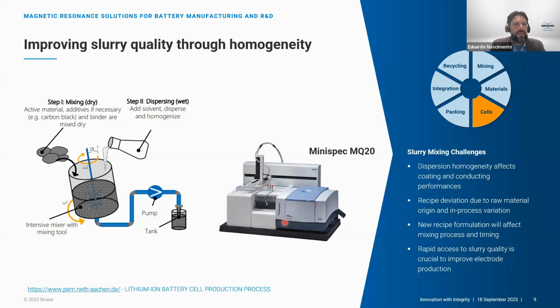Of course, we know there is a great potential for the dry coating process to take place here as well, where we also keep an eye on the development of new solutions. But so far, we see that most of the companies are still relying on mixing for the electrode manufacturing. And then the homogeneity of the slurry plays a big role here, because this can affect the coating process and also the conducting performance. So I will demonstrate here how TD-NMR can help with that.